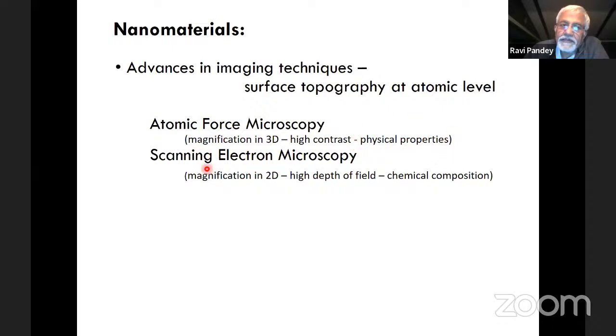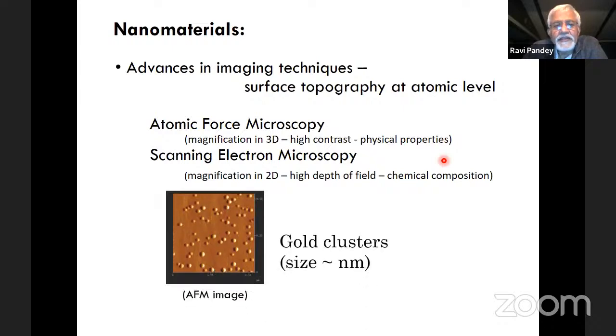On the other hand is SEM, where we have 2D magnification, and because of it a high depth of field, which provides information about the chemical composition of the material. So these are the two major tools which have helped us move towards the nanomaterials or nanotechnology area. And here is one of the AFM images where one is looking at gold clusters. You can count the size in nanometers, these clusters sitting on a silicon carbide substrate.